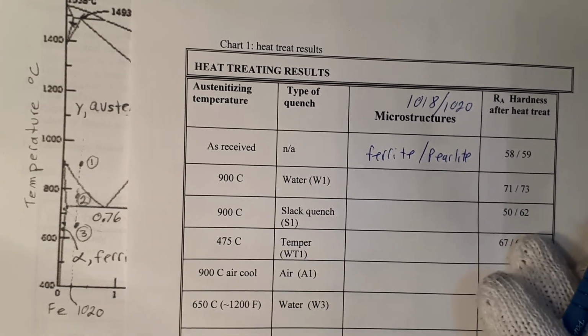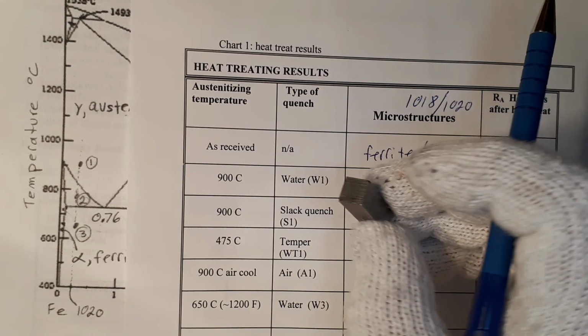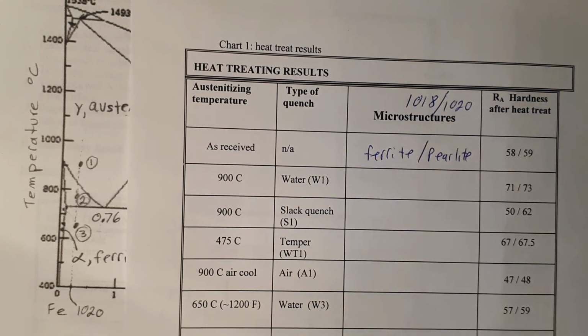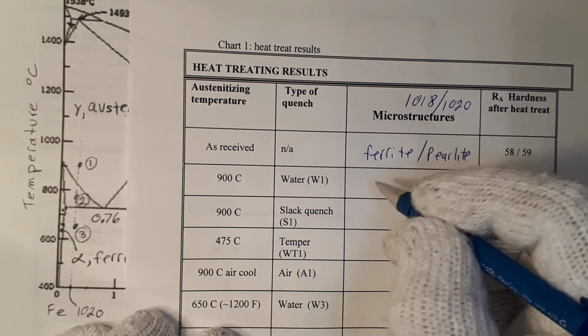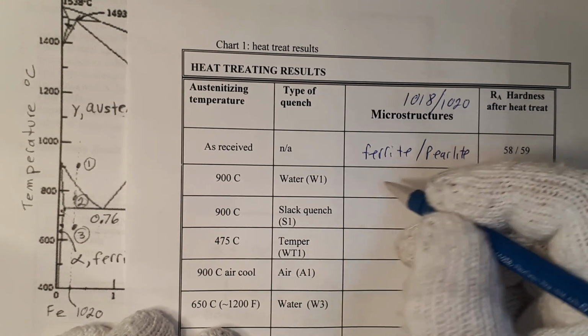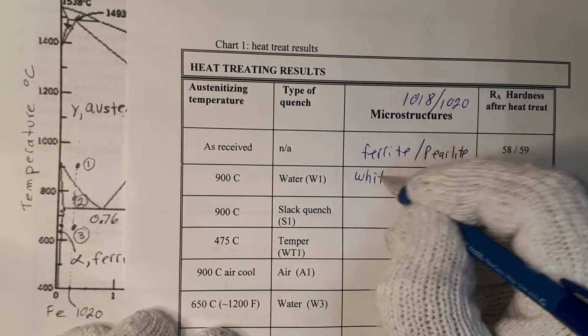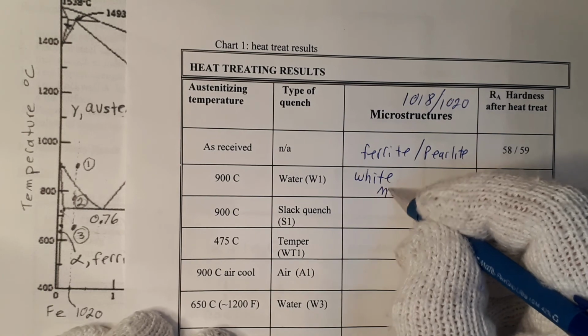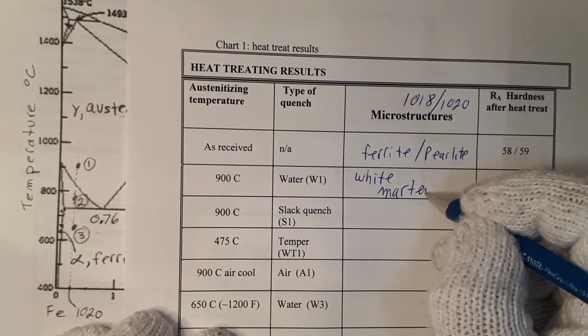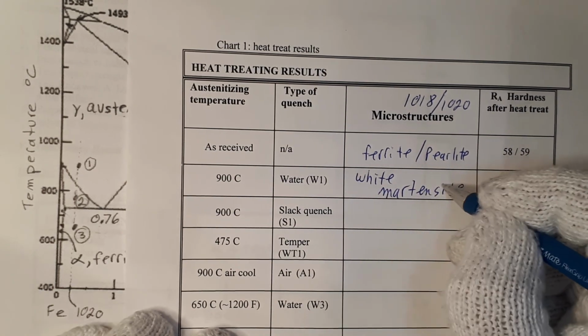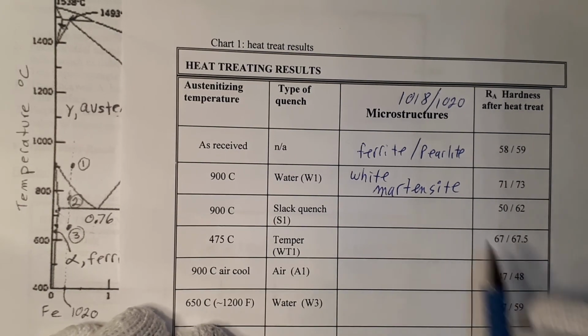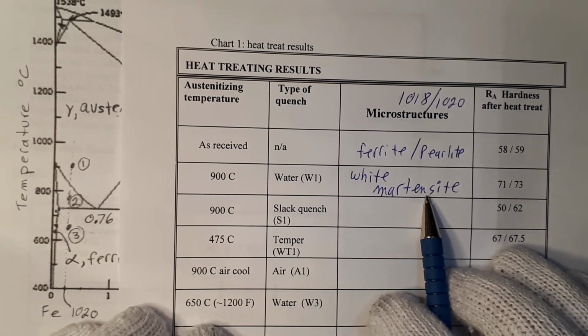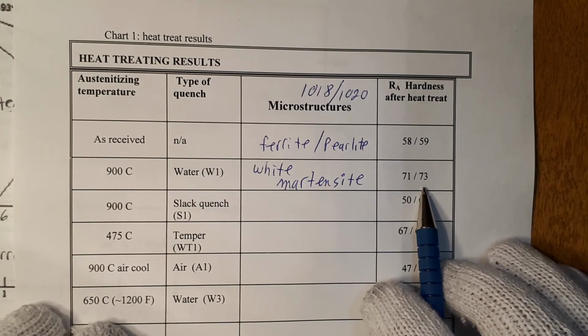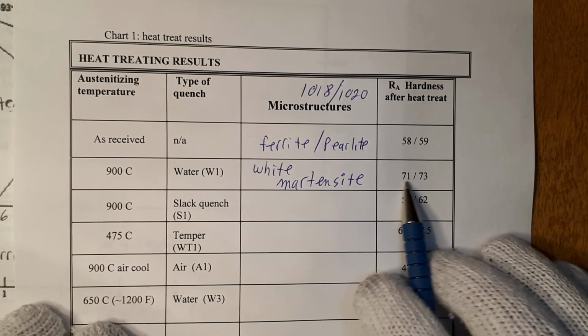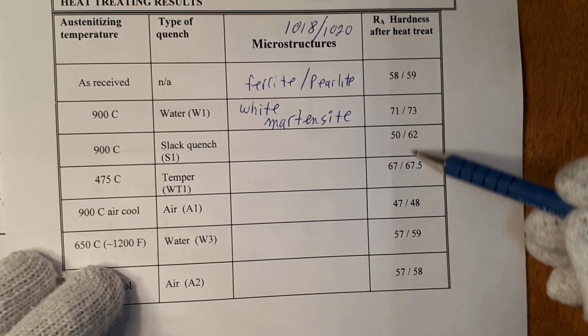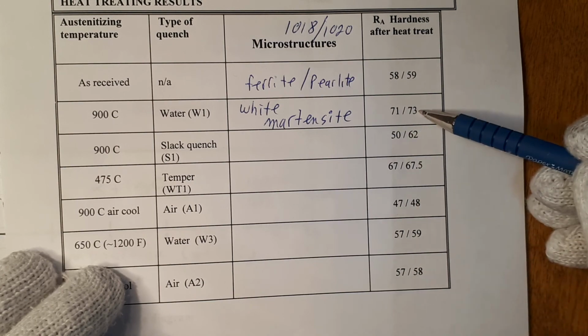In doing so, the microstructure that would have formed after quenching, if you were to take that sample after quench, would be martensite. This has a special name. After quench, it's called white martensite. It's a very brittle structure, also very hard, and you can see that here in the hardness. It should be the hardest in all of this column, and as you can see, it is the hardest.